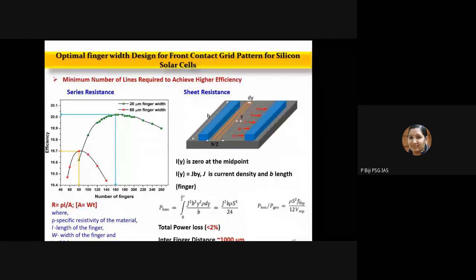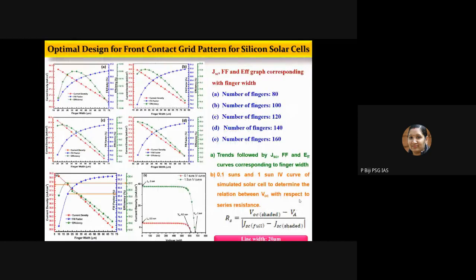The total power loss was calculated as less than 2%. And we also optimized the interfinger distance, which was found to be 1000 micrometers. Then I will quickly go through. We also optimized the number of fingers for 20 micrometer line width, from which we understood that the 20 micrometer finger width with 160 fingers could show enhanced fill factor as well as enhanced efficiency. So the optimal dimensions are a line width of 20 micrometer and an interfinger distance of 1000 micrometer.